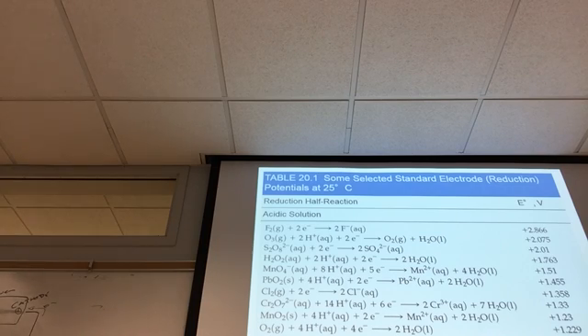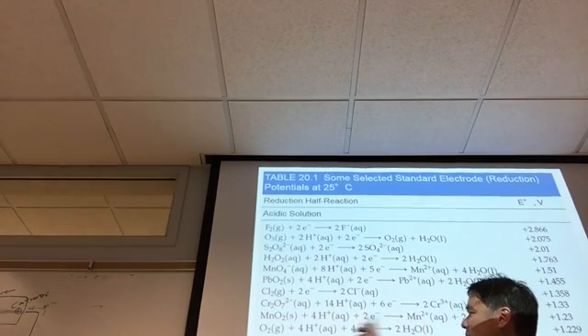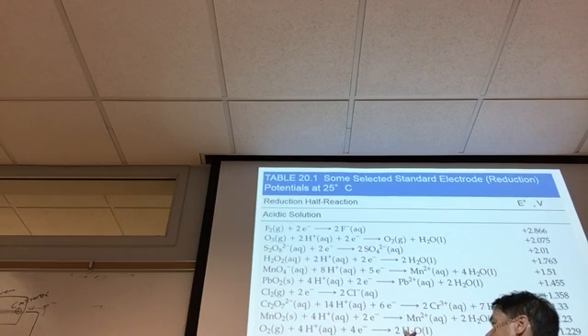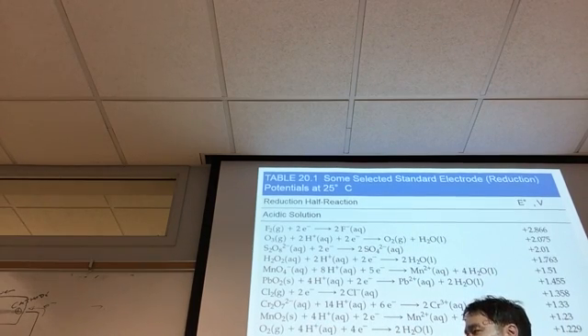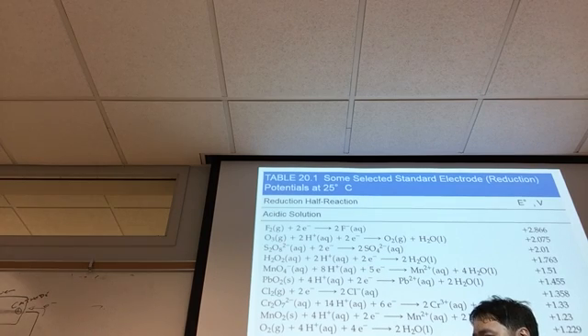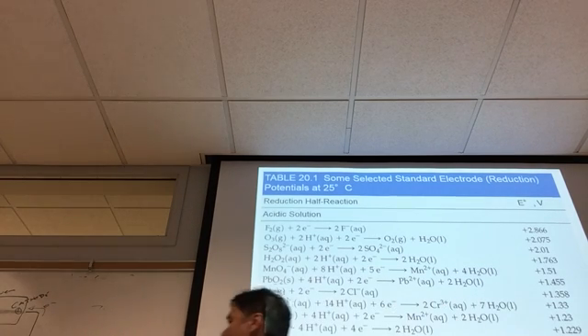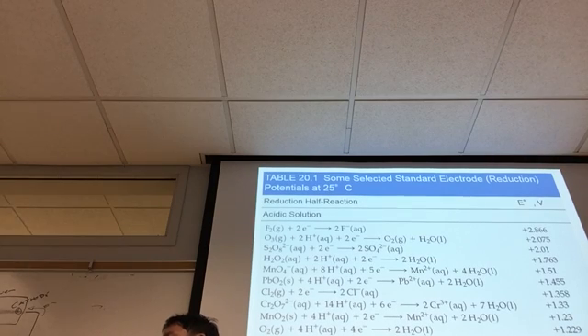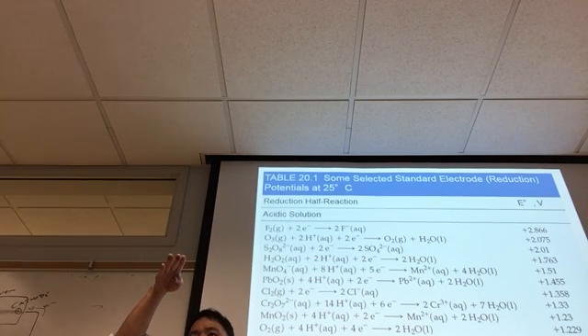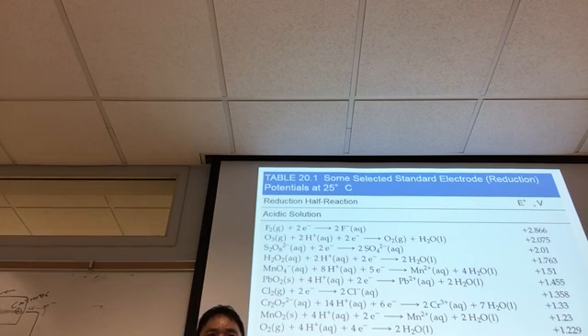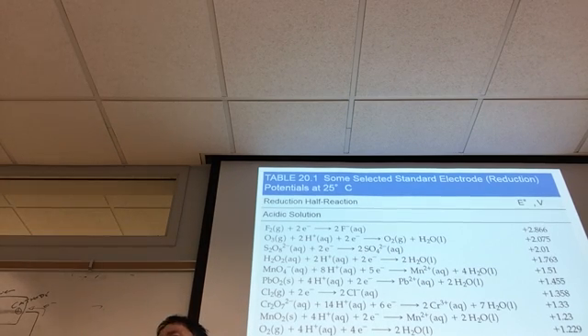Even though it's more work, kinetically it's less, because to oxidize water, you have to break bonds and make new bonds. Because to oxidize water, we've got to form O2 and H+. And so we're breaking bonds and forming new bonds. And so the activation energy to oxidize water is much higher, even though you'll get some of that energy back. Whereas the activation energy to oxidize chloride is very low. And so this has a very low activation barrier because you're just plucking an electron off the outermost shell. This has a much higher one.